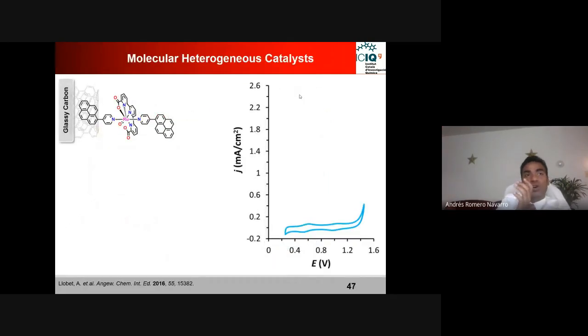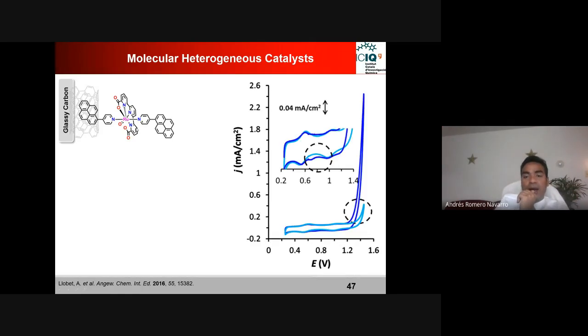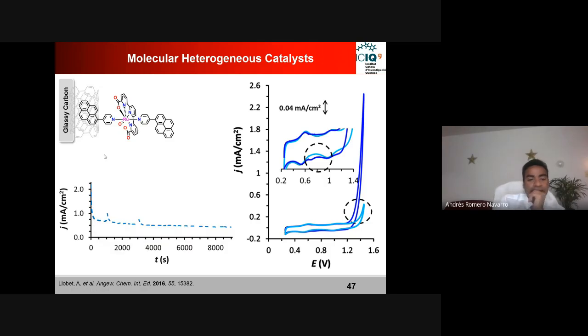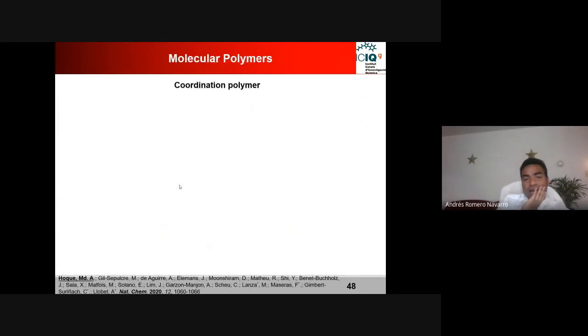So then they thought, okay, we want to immobilize that molecule onto a surface in order to design the water splitting device. And then they anchored that one, and they found that they are getting a current density of less than 1 milliamp over more than 2 hours. But again, as I was saying, our demand is to increase this current density above 10 milliamp per centimeter squared. Then I thought, okay, can we do that? And if we can, then how?